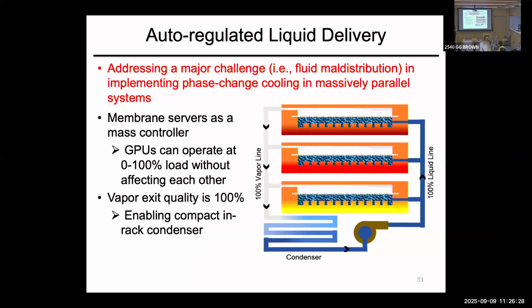The other challenge we never talk about is that two-phase flow is a function of pressure drop. If you have a constant pressure, and one GPU is generating a certain amount of heat versus another, you get a significant pressure increase. Obviously the membrane mitigates that, but you still get maldistribution. What is beautiful about this membrane is that if you apply constant hydrostatic pressure, the liquid stays in these pores separately, and essentially heat can be applied at any rate.